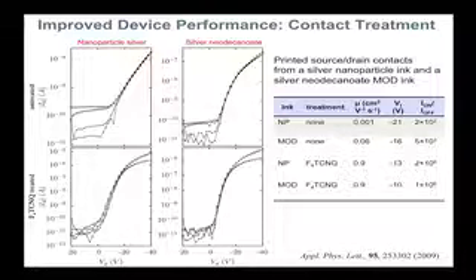You see that these two TFTs are very bad TFTs. They have very high off currents, and they don't turn on very sharply. You can see here the mobility is very low for these two cases here. So if you're a chemist and you spend a lot of time preparing your super semiconductor, and you give it to somebody who makes a device and tells you the mobility of your material is very low, I tell you, that may not be true, because what a device tells you is how good the device is, not how good the material is. So here is a very good material, but the device was a bad device.